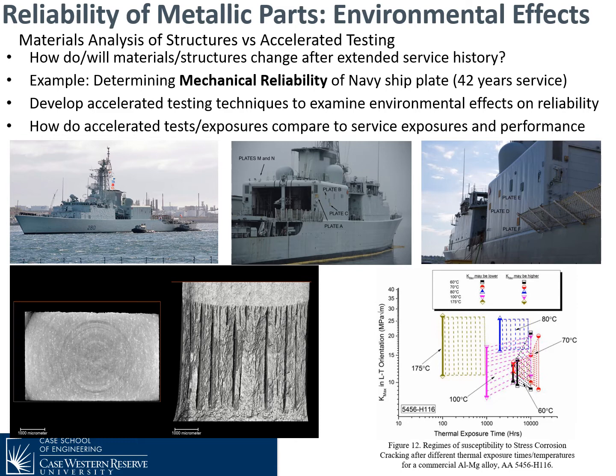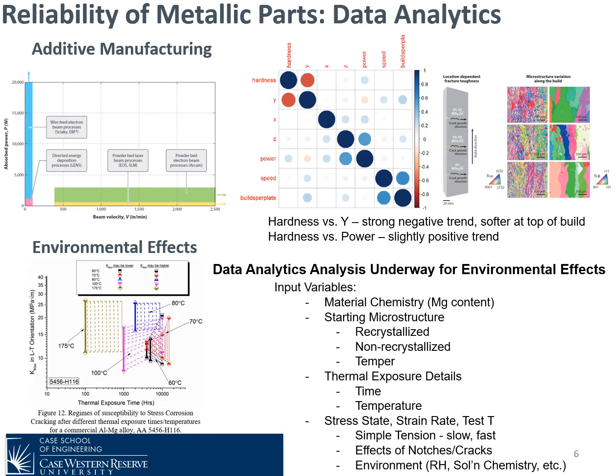And so anywhere you see colors, you see that materials thermally exposed under those conditions will exhibit extreme stress corrosion cracking. So at high temperatures, it doesn't take very long for this to happen. At lower temperatures, it takes longer. But the exposure of this ship and other things like it will have exposures out to 60°C, even for many years. So let me finish with how does the data analytics present itself here?